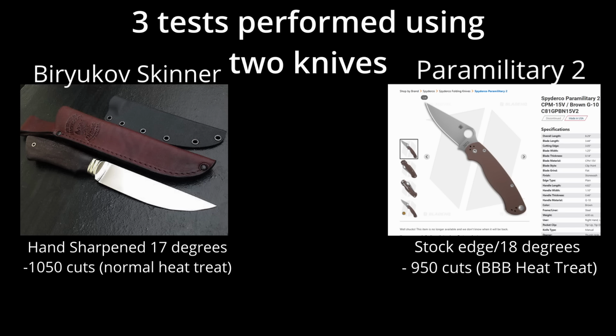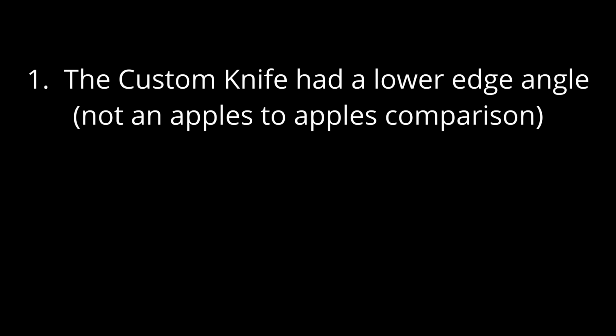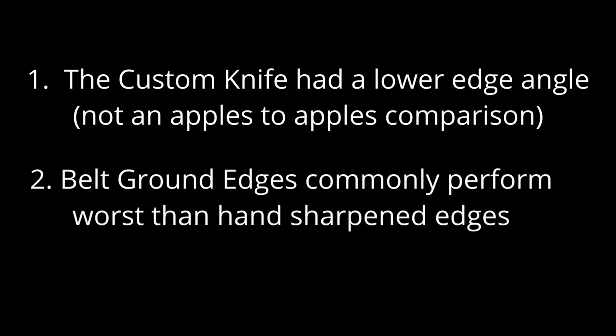Some might even say that this disproves that the Big Brown Bear heat treat protocol even does anything worthwhile, but they'd be wrong for 2 very distinct reasons. Number 1, the difference of 1 degree per side is a significant difference in toughness and geometry-based edge retention. And number 2, it's not exactly fair to compare a factory belt ground edge against a hand-sharpened and polished edge.